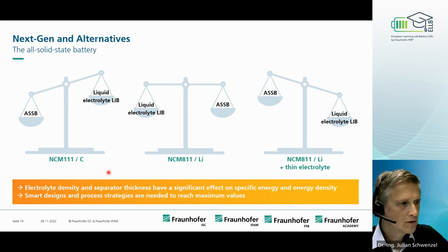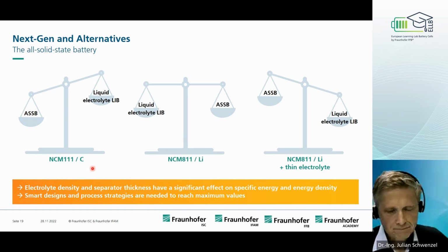So the key message is that the electrolyte density and the separator thickness have the most significant effect on the specific energy and energy density. So a smart design and process strategies are necessary to reach the maximum value of this technology.